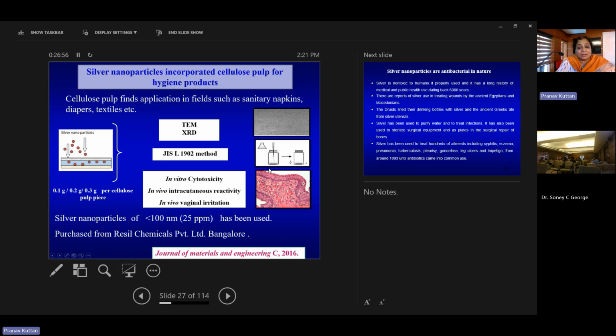Here we characterized the silver nanoparticles using TEM. XRD also was used. Then we gave the material for testing of antibacterial activity using the JIS L1902 method. This is a method which was developed in Japan for testing textiles. The antibacterial activity of the textiles is tested using this JIS L1902 method. Then different tests were done: cytotoxicity, in vivo intracutaneous reactivity and vaginal irritation. Because this product is going to be used in diapers and sanitary napkins, vaginal irritation was checked.